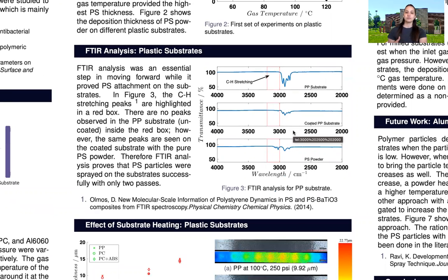Since we only did 2 passes with the plastic substrates, we wanted to make sure we're actually depositing polystyrene powder on the surfaces. Therefore, we ran an FTIR analysis on the surfaces. Figure 3 shows the results of FTIR. The top graph shows the polypropylene surface as it is with no carbon hydrogen stretching. The second graph shows the coated polypropylene surface with carbon hydrogen stretching peaks appearing. And the third graph is an FTIR graph of the pure polystyrene powder for comparison. You can see the carbon hydrogen peaks here.